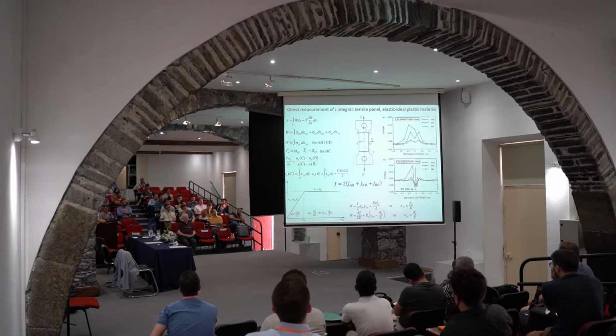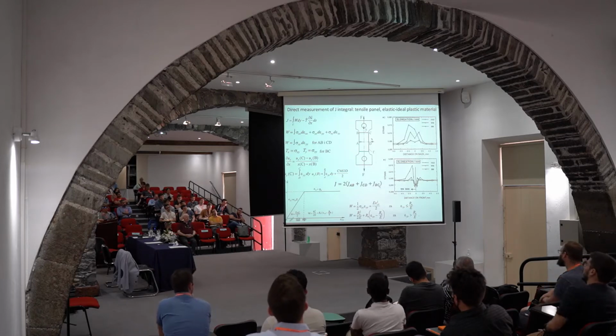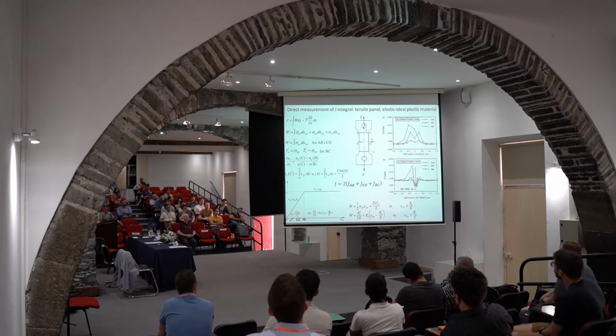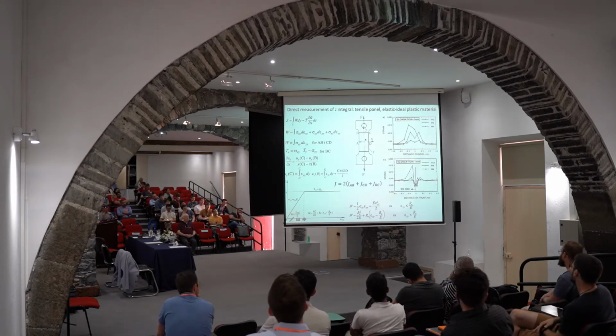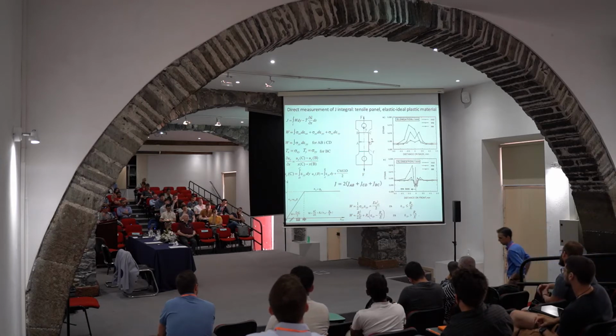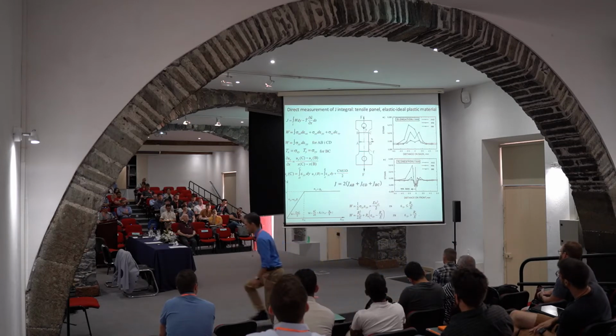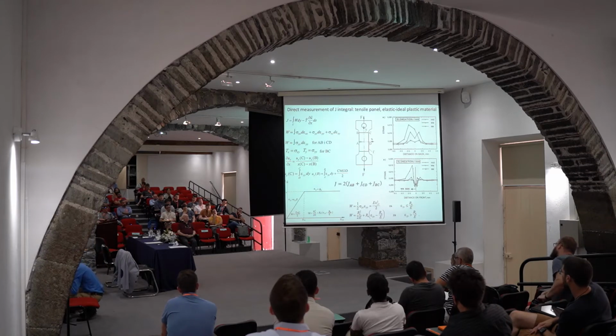Now, the point here is that, let's say, a tensile specimen, as shown here, we can use to measure strains along points from here to B, and then from C to D. This is what is available. Those are outer surfaces. And interestingly enough, if we express J integral in its terms, we find out that those strains measured along this path and along this, of course I'm using symmetry, so not all the way, just half of it, are enough.